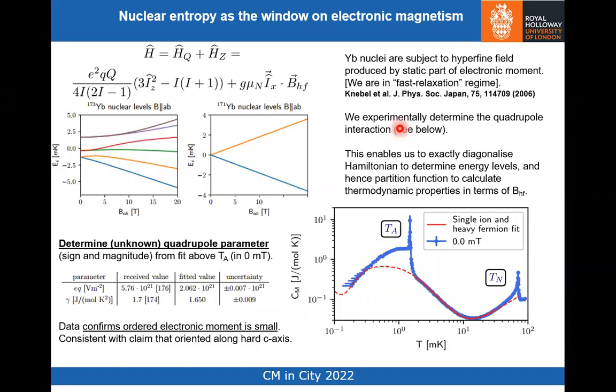Let's look at that then. This is what we believe is happening. We're using the nuclear entropy as a window on the electronic magnetism. The nuclear spins have a quadrupole interaction for 173, which has a quadrupole moment. And both species, 171 is spin a half, so no quadrupole moment, have a Zeeman interaction with the hyperfine field. The origin of the hyperfine field is that we're in the so-called fast relaxation regime, so the ytterbium nuclei are subject to the hyperfine field produced by the static part of the electronic moment.